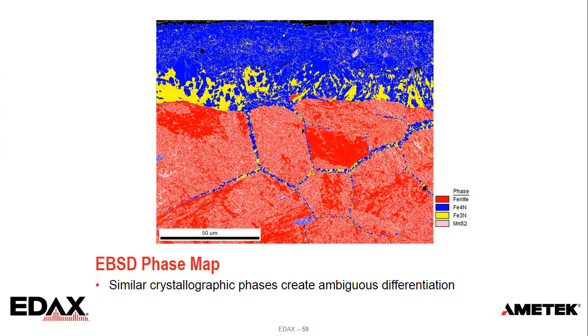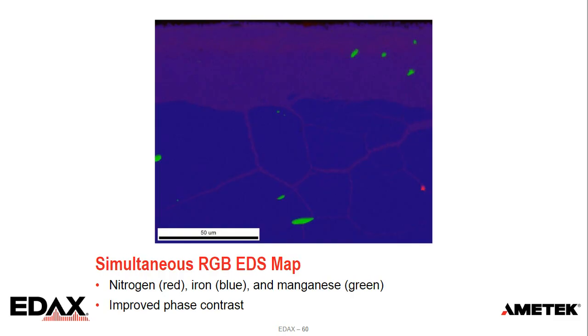If we look at the phases, we see here there's the ferritic phase in red. There's the blue and yellow phases are a couple of the nitride phases, and then there's a manganese sulfide phase as well. But it has some trouble differentiating these. There's some speckling within the base ferritic grains. So with that, we use what's called simultaneous EDS collection for chi-scan or chemical indexing scanning.